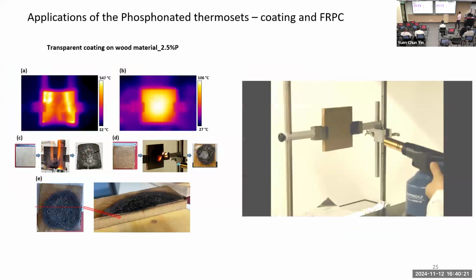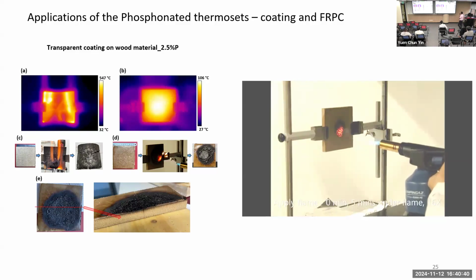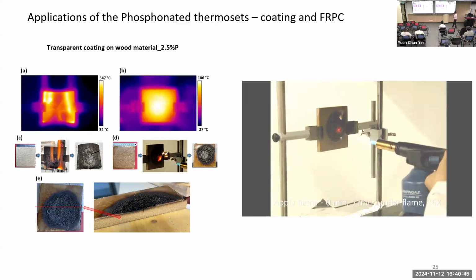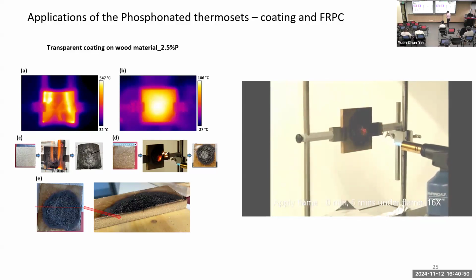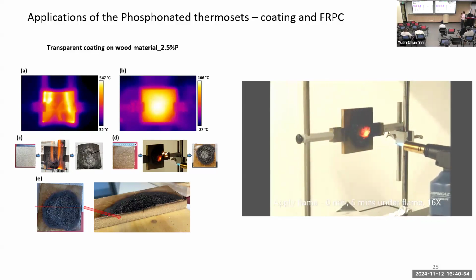So we looked into different applications. One of the applications was to apply this thin coating on wood surface, where you can see on the left, there is an IR camera at the back. You provide a flame on the front, which you can see in the experiment. We apply like 5 minutes of flame, and you can see the maximum temperature recorded at the back of the material, which has got this coating, is not more than 100 degrees, I would say.